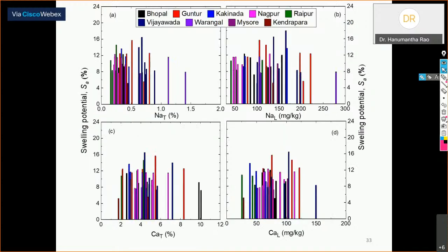Similarly, we also tried to draw the relationship for swelling potential as a function of the total sodium or the total calcium or the leachable sodium and the leachable calcium. Again, they have a tremendous implication, especially to identify the potential chemical additive so that your swelling potential is minimum when you treat that particular expansive soil with the chemical additive. These are the relationships of swelling potential versus sodium and calcium chemical elements.